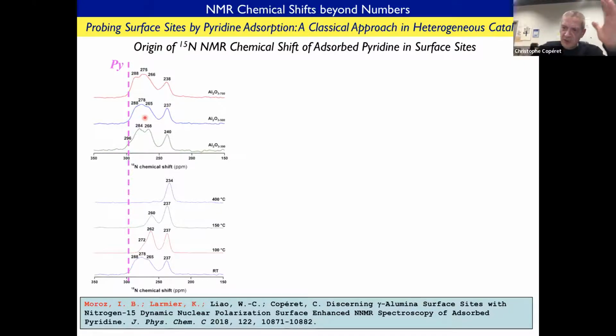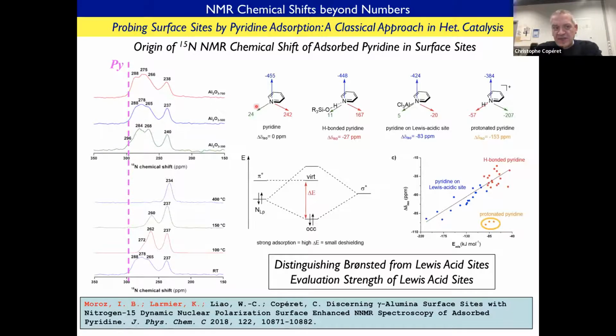Again, by doing the same approach as what I've shown you earlier on organometallic compounds, we can show that the origin of this shielding is due to the fact that when you interact pyridine with either an H atom, which is a weak Brønsted acid, H bonding with nitrogen, or a Lewis acid, you actually quench the delta 11 because you interact the Lewis acid with this lone pair, which is the origin of this very high chemical shift value for pyridine. So if you make a bond between pyridine and a Lewis acid or an H bond, you will quench this lone pair, and by quenching the lone pair, you will decrease this chemical shift.